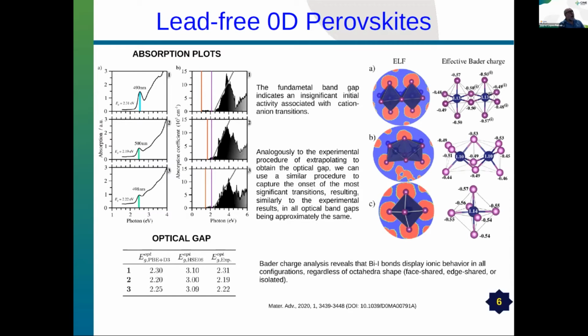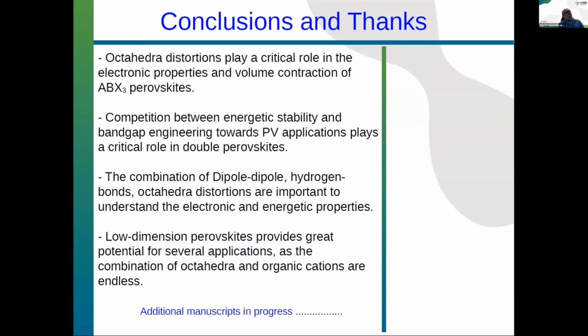Okay? With that in mind, I come to the conclusion of my talk. As you can see, we explore from the simple, basic structures up to the complex structures, and it provides us a quite good understanding that the octahedral distortions play a critical role in the electronic structure properties. The competition between energetic stability and band gap engineering is a critical point here. It's really important to say, because we can improve stability and electronic properties.